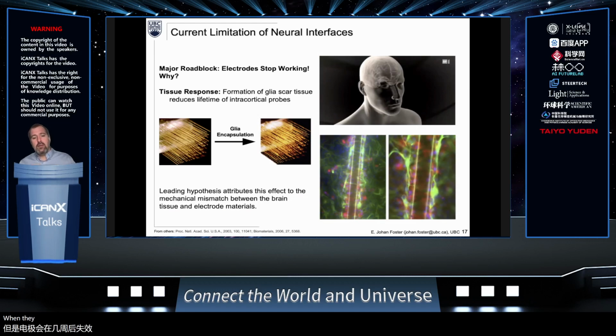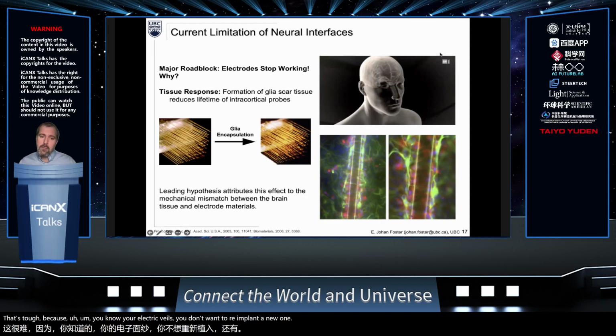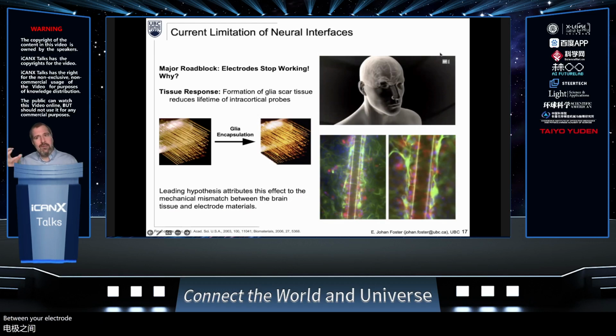When they took the electrodes out, they saw that there was scar tissue around the electrode. Now, that's tough because your electrode fails. You don't want to reimplant a new one. And the hypothesis was it was the difference in stiffness between your electrode, a very, very stiff material like tungsten and steel, inside of your brain, which is very, very soft. Think the texture of a jello or a gelatin. And that mechanical mismatch was a problem.